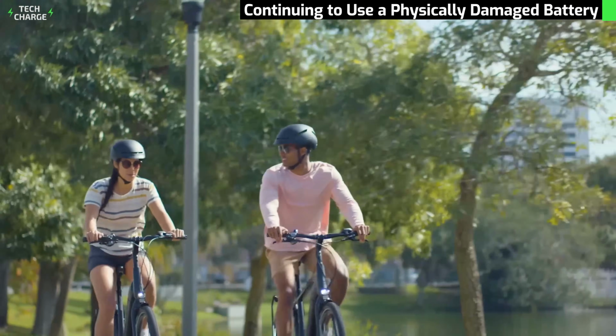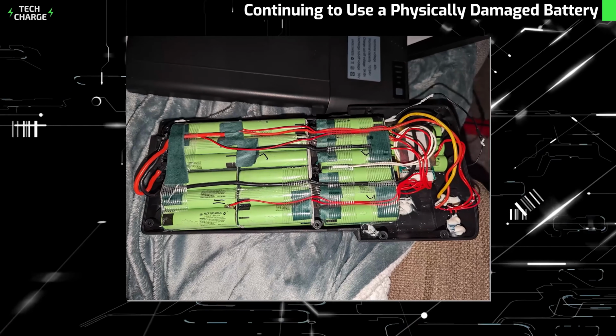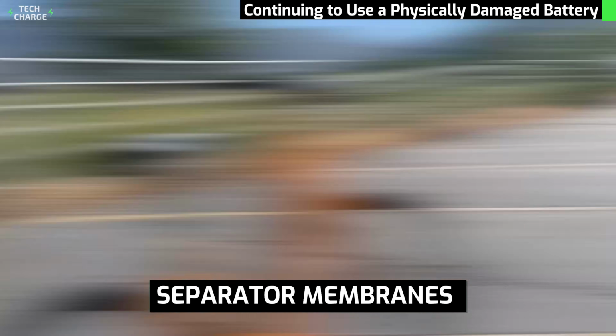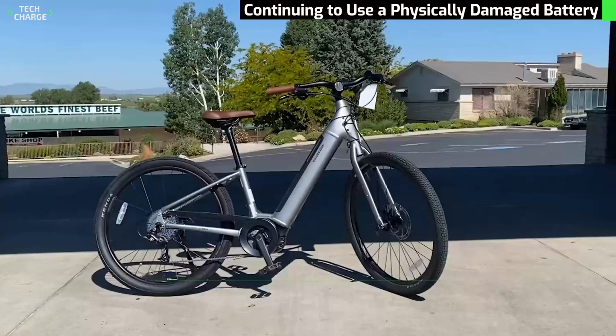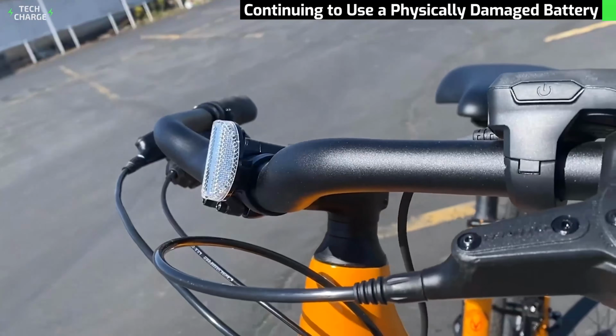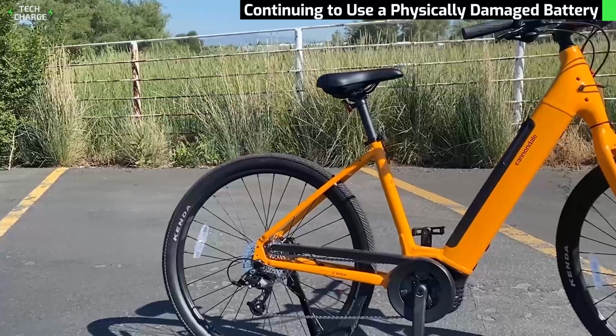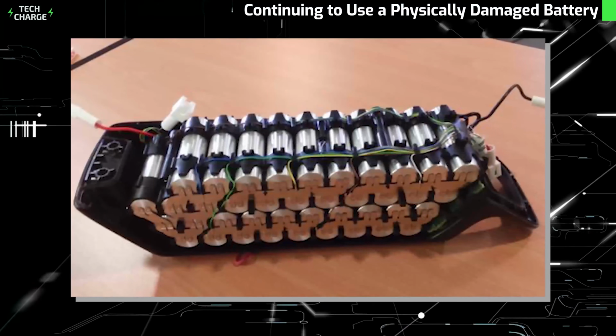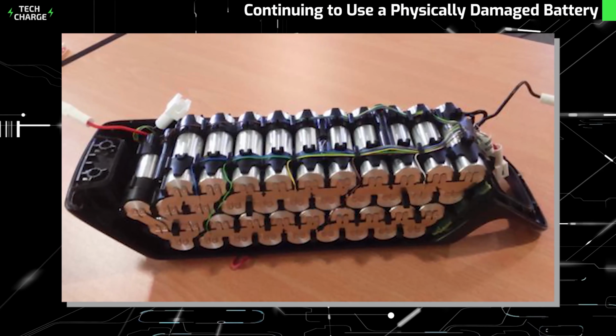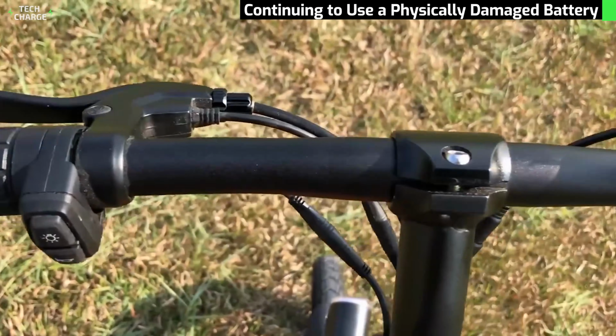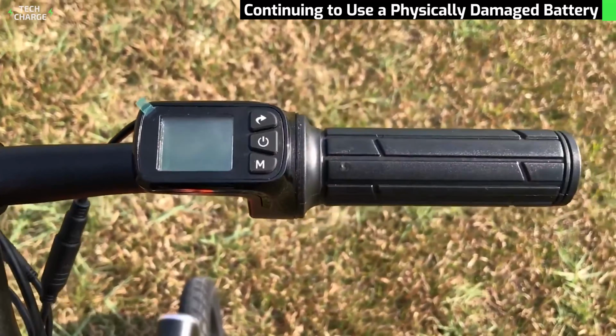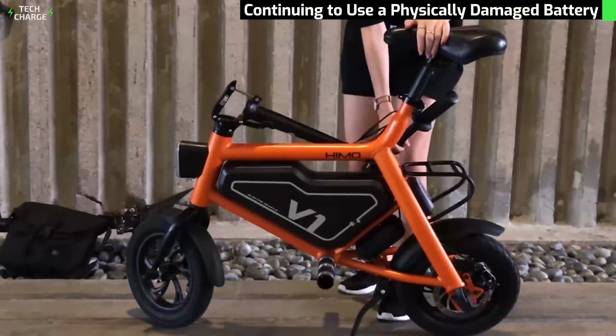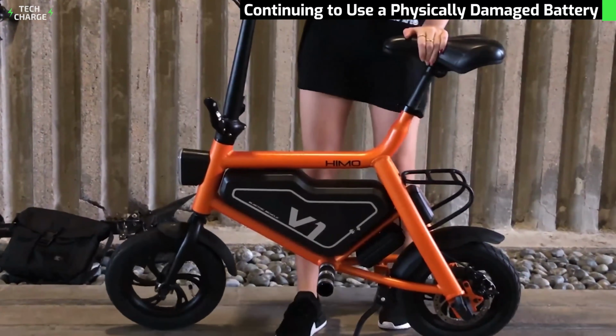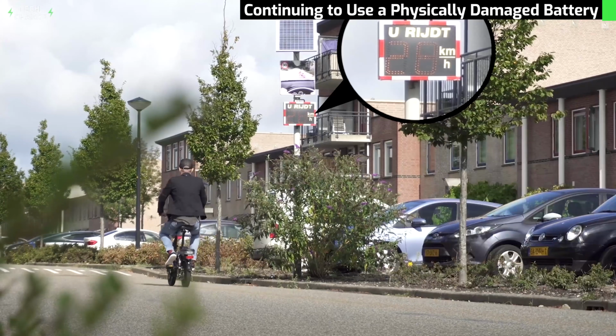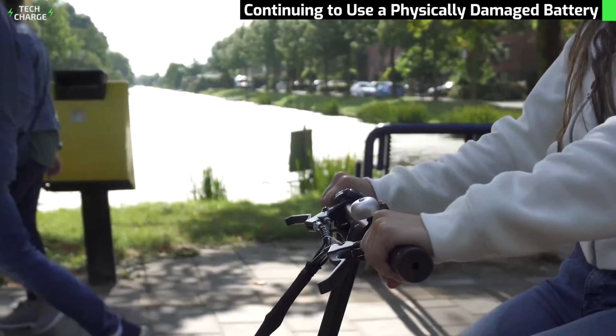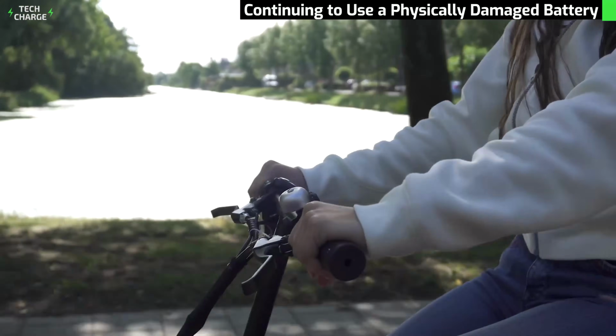The internal structure of a lithium-ion cell depends on extremely thin separator membranes to keep the anode and cathode materials apart. Mechanical stress from impacts can compress, tear, or puncture these delicate membranes, creating internal short circuits. The timing of failure after mechanical damage is unpredictable, and that's what makes this mistake so dangerous. A battery might function normally for hours or even days after a hard impact before suddenly entering thermal runaway.